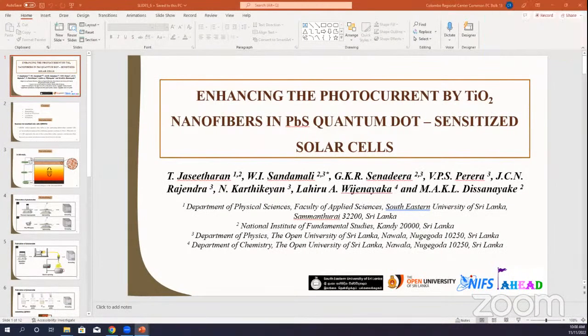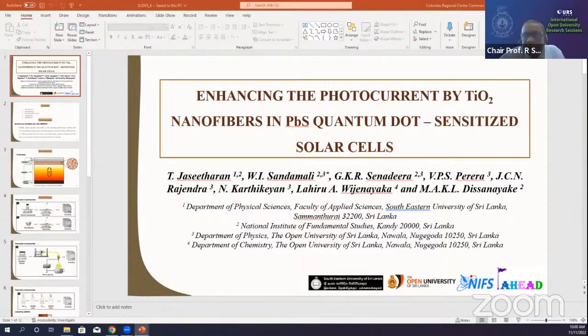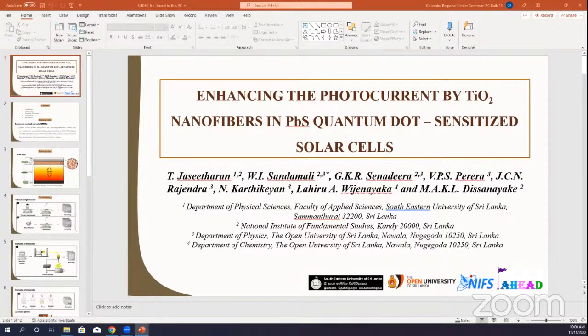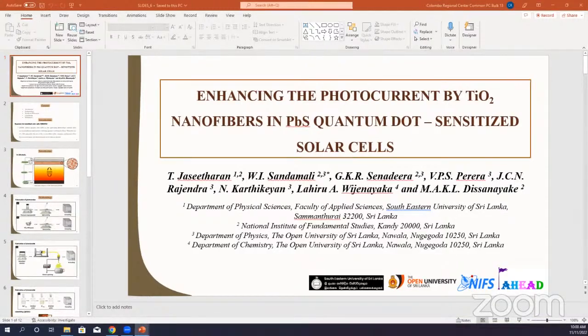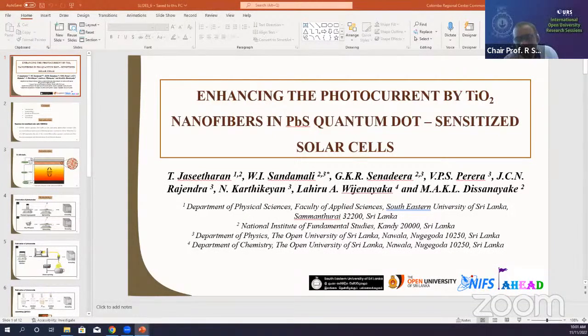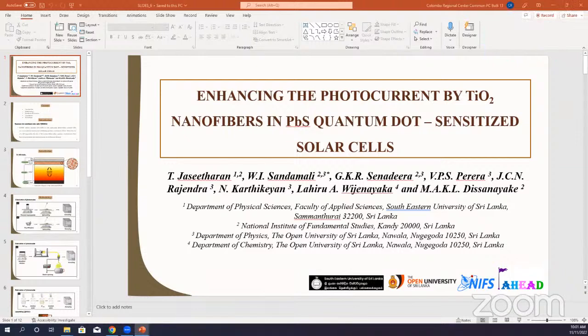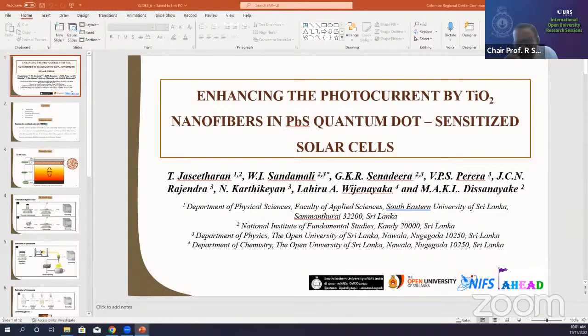Yes, in the case of lead sulfide, for example, in the dye-sensitized solar cell, one dye molecule will give one electron hole pair for absorbing one photon, but this has the ability of multiple exciton generation in the quantum dots in the lead sulfide. And it has a wide range of absorption from visible to near IR. Then we can harvest most of the sunlight. Did you try with some other metal, for example, tin, in the same group in the periodic table? Yes, we already did SnS, you mean tin sulfide. The efficiency is very low compared with PbS lead sulfide.